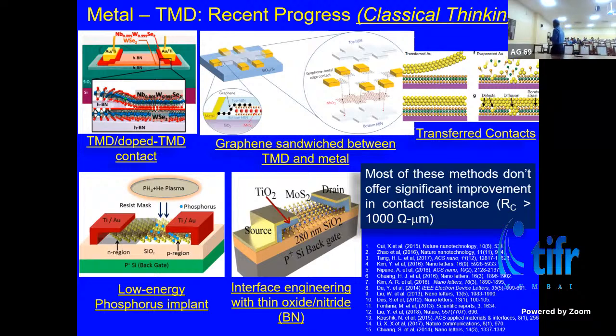Now, how do you dope in bulk semiconductor? You either diffuse impurities, and this is bulk semiconductor, so there's a lot of volume for impurities to diffuse, or you implant impurities and then activate them through some kind of a thermal annealing process, right? And again, that's bulk, so you can implant. But 2D is a one atom thing, 1 to say 3 atoms. If it is transition metal dichalcogenides, we're talking about 2 chalcogen and 1 metal layer, say 0.7 nanometer thickness, right?